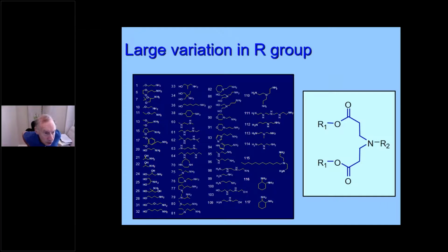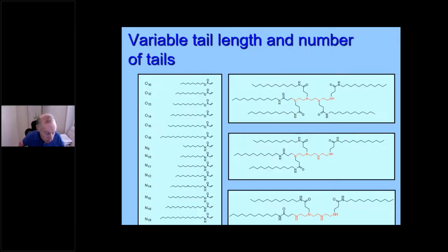We had very large variations in R groups. But what we would use actually was a Michael synthesis where we could take conjugate diacrylates with amines. So that was the key, that we would mix these with, and the next slide just shows some additional things that we did. We could not only change the R group, but we could change the tail length and the number of tails. You see 5, 4, and 3 tails on the right. And when you do this, next slide,